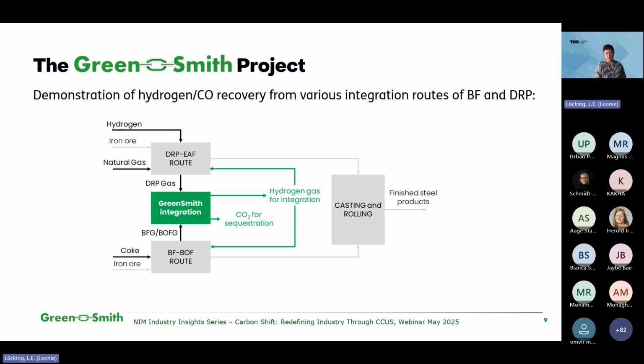The idea behind this was that we look at the progression of the steel industry and how it can build. So we have the traditional steel mills with blast furnace and basic oxygen furnace. And if on site you want to slowly move towards direct reduction, which has an improved efficiency, how can we integrate these to get the biggest benefit? For example, can we use the off gases from the direct reduction route as input into our blast furnaces? And can we use the outlets of the blast furnace as input for our direct reduction? So these were the thoughts with which we went in, in order to really reduce the need for carbon in the process, and so recycle as much as possible internally, and also capture to reduce the overall carbon footprint.